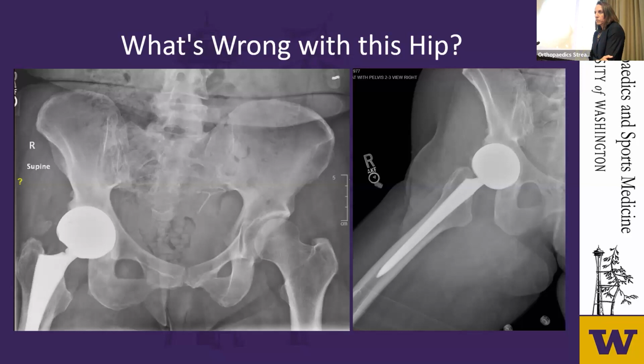And this isn't something that happened once. This was probably happening almost every time she took a step. And quite honestly, this is something where at the first revision, this is probably something that should have been fixed then. The resort to swapping out the bearings, I think, was really not fixing the problem. The case here was to swap out the socket at the very least at that early stage, without getting a better sense of what the stem looked like. If it was sort of a one-time dislocation, you could probably have gotten away with leaving the stem, but once you have a notch like that, it's got to go, no matter what.